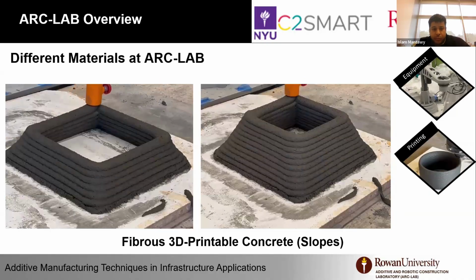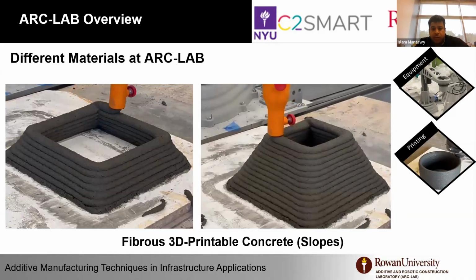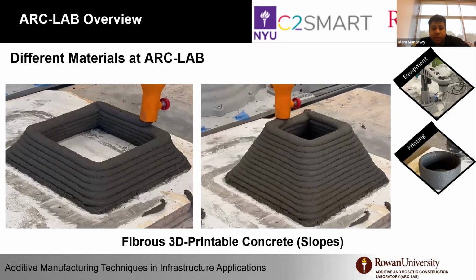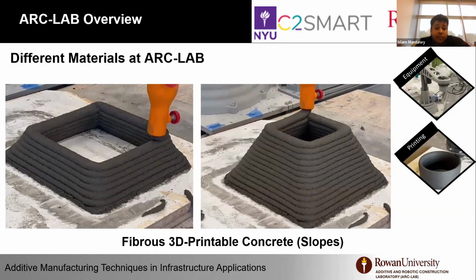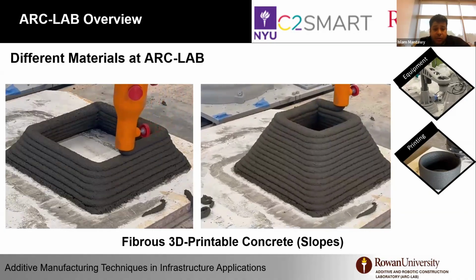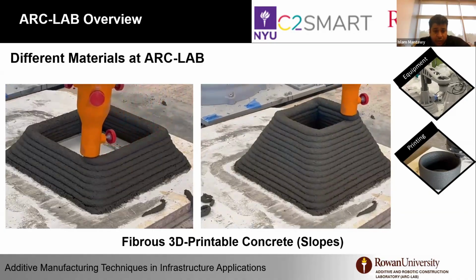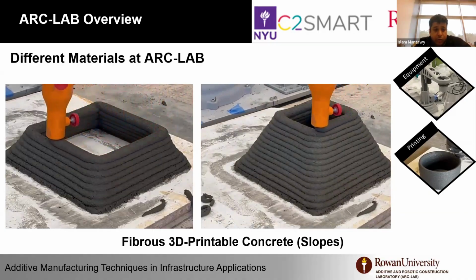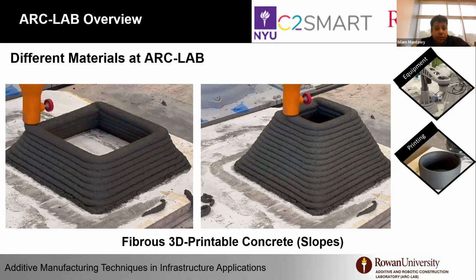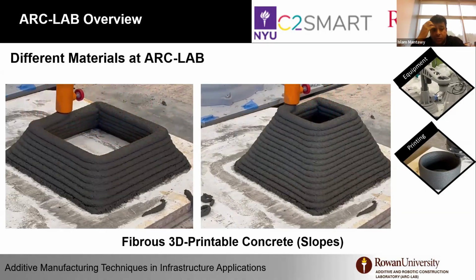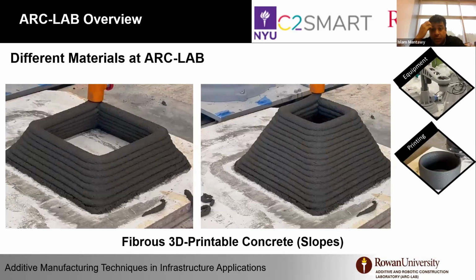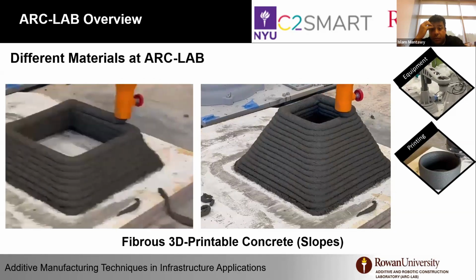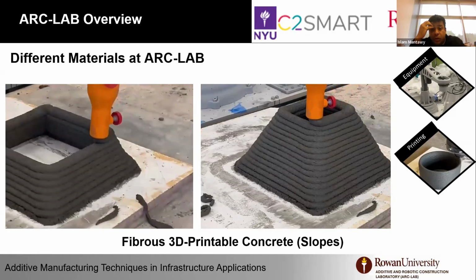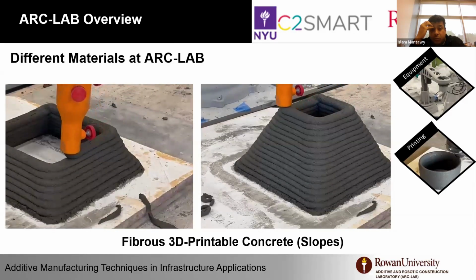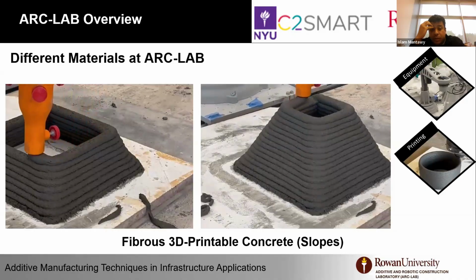We also did a lot of work where we try to examine the slope stability. This material does not use any accelerator, so it relies on the exothermic reaction and heat of hydration that kicks in later, with continuous curing. The material showed really extraordinary application with different slopes, as you can see here. This is a moderate slope of 26 degrees from vertical position, enabling us to print various designs for pyramids. And this one was also with steel fibers.